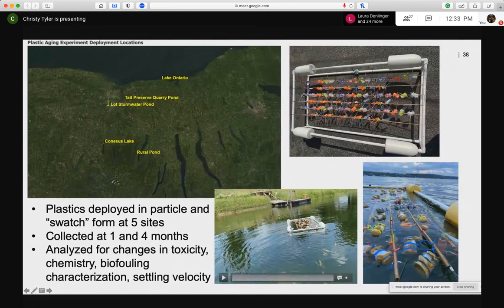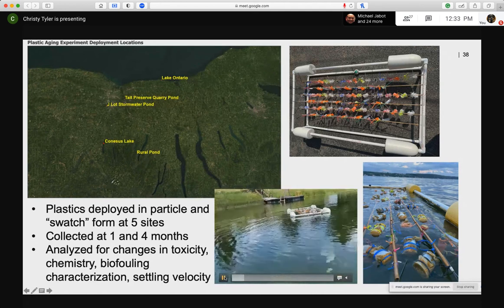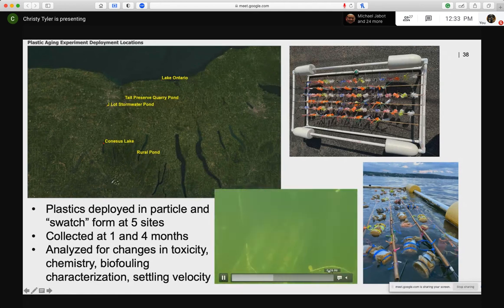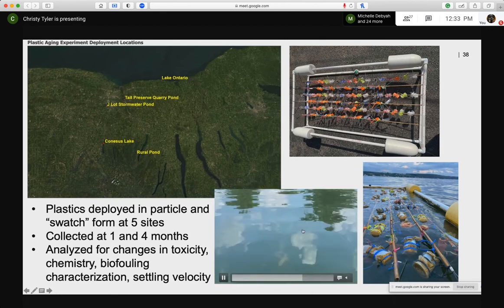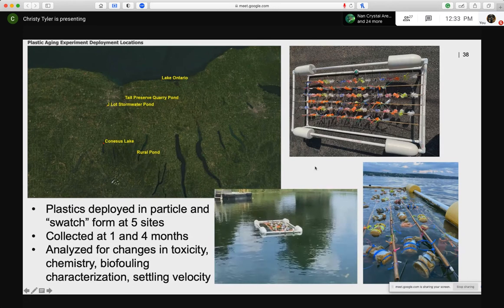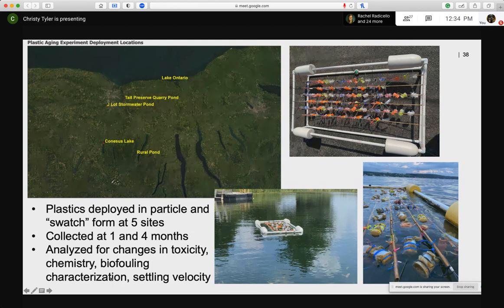And then they were deployed both at the surface and also, as you can see down at the bottom of this pond, we're also deploying them at the bottom. So these were set out at the beginning of July at these locations, and then we're sampling them. So far, we've sampled after 1 month and after 4 months. They're still out in the environment over the winter, and we'll be sampling again next summer to get a roughly 12-month sampling point to look at changes in toxicity, chemistry, biofouling characterization, and the settling velocity. Right now, we're going to just present some preliminary data because we're still working through a lot of these data.